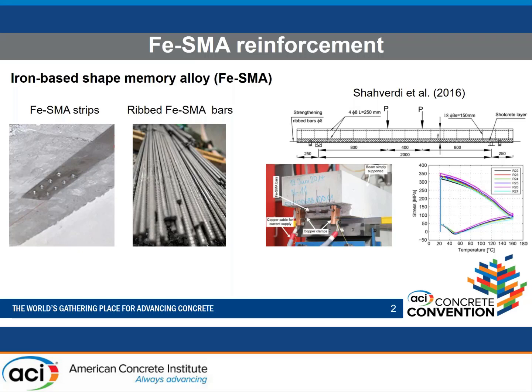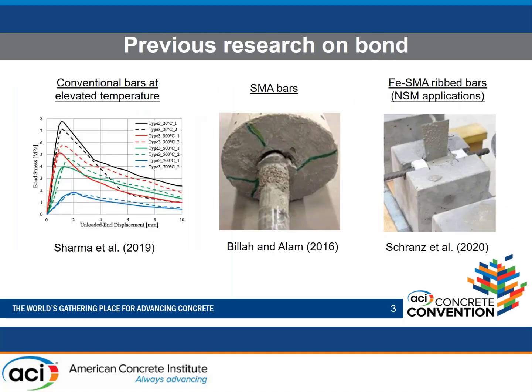And recently, a new material was developed. It's iron-based. It's cheaper. It doesn't have the superelastic property of nickel titanium-based alloys, but it still has the shape memory effect. As we can see here, we have them in strips. We have them in ribbed bars, similar to conventional steel rebars. Here we have a study about strengthening a beam using those bars. What they did, they provided a shotcrete layer, and they embedded those bars, and they used heating activation in order to induce a pre-stressing force in the beam, and that resulted in improving the cracking moment capacity and the performance of the beam. With that being said, this material is being used more and more, and different researchers are investigating it. And for that reason, it's important to understand the bond behavior of this material.